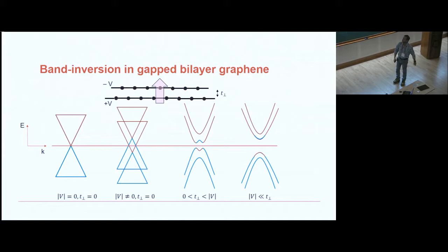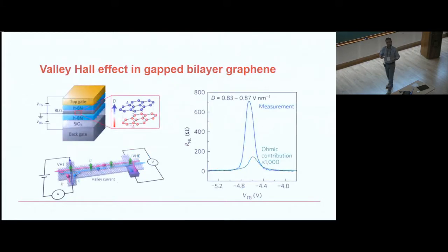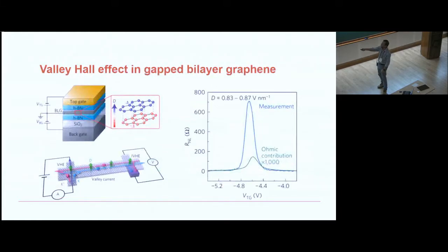Okay, now that means that we will have very similar kinds of transport that people have seen in the case of topological insulators or the inversion symmetry broken single layer graphene. And indeed, I'm really sorry about it, but I put the references, but it's gone. Two groups published this work in 2015, and they showed that if I have a bilayer graphene and apply a large electric field, exactly the way the non-local voltages are generated in single layer graphene, over here also we get a very strong non-local voltage generated when I apply current here, and the valley current moves in a perpendicular direction and produces voltage at completely separate places.